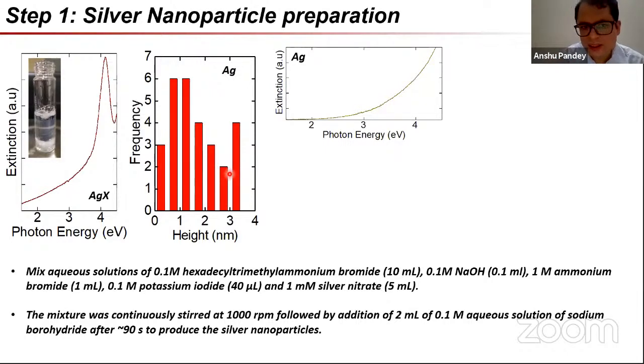The silver, again, is not some magic size silver particle that we are working with, but at least as far as the AFM tells us, these are done by casting these silver particles onto a mica substrate, where then using AFM their sizes are determined. We find that there's a distribution. Most of it is certainly peaked around 1, but the distribution you can see is quite broad. It goes all the way to 3, and there is even a spike after 3, which is undesirable, but that is what it is.